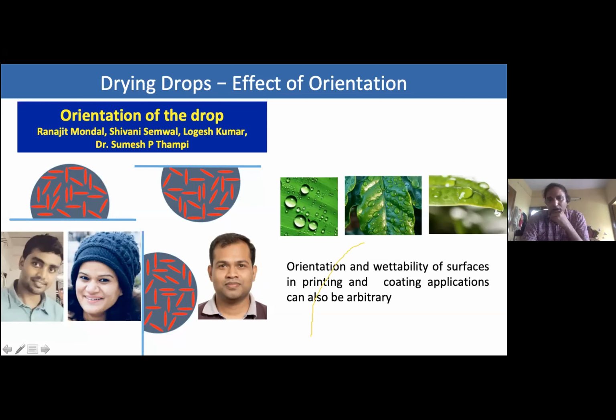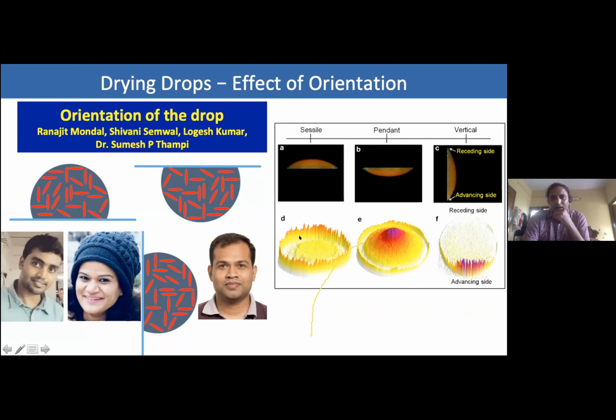Typically, if you look at leaves, most of the leaves are hydrophobic, right? So one would also be interested to look at drying drops at different orientations. In some of the recent work that we have done, we have shown that under certain conditions, the sessile drops give the coffee ring effect, where particles deposit at the edge. If you dry the same drop in the pendant configuration, we see accumulation of more particles in the center, what is called a central dome formation.